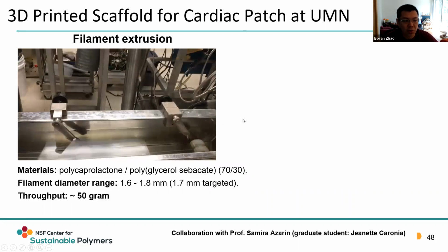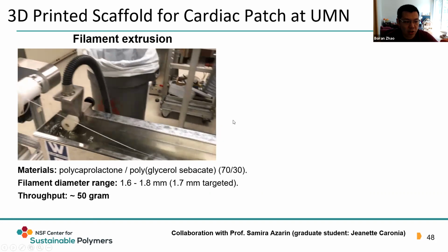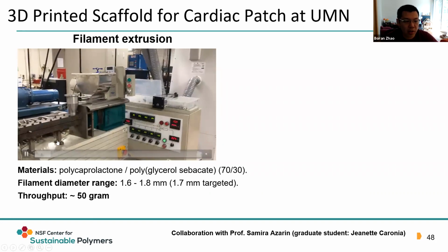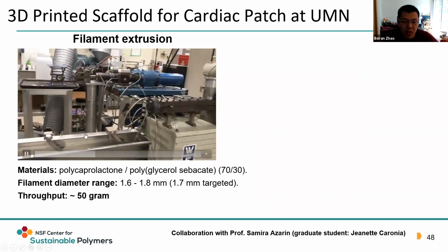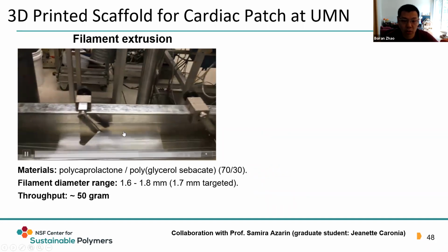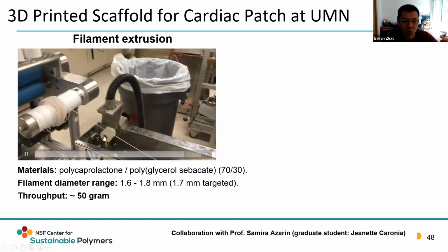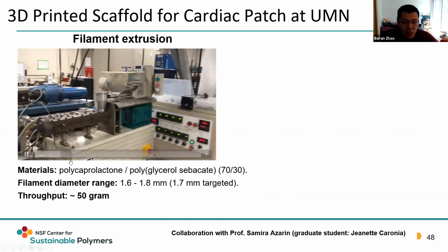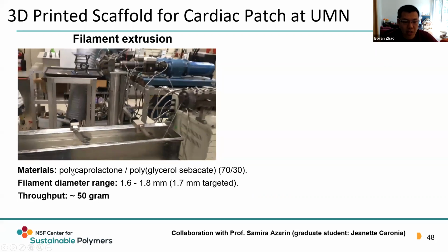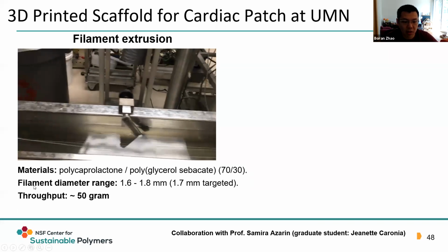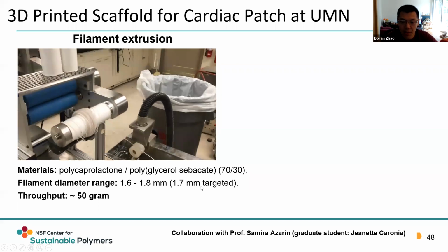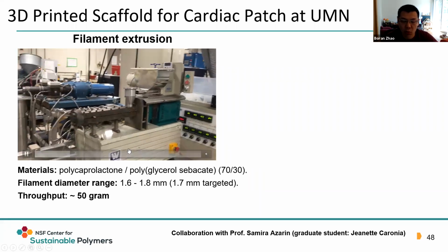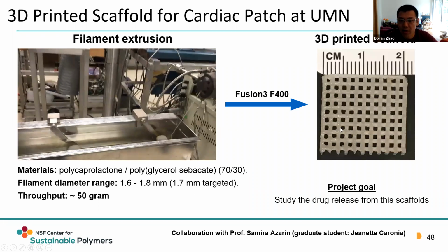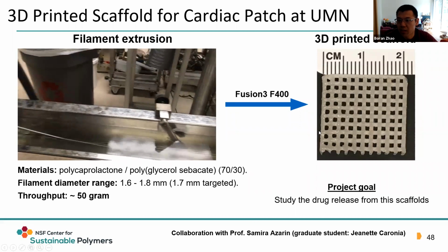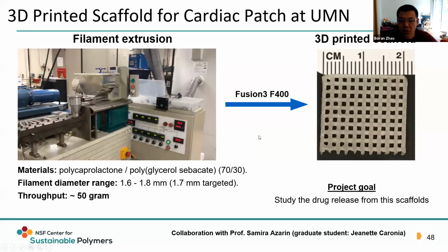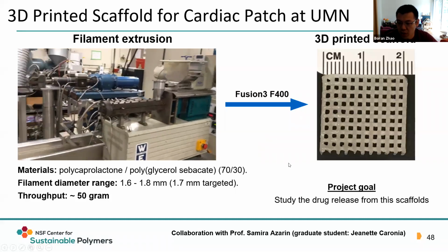The goal here is to 3D print a scaffold as a cardiac patch using FDM. And as shown in the video here, we use the twin screw extruder to make the filament. This is exactly the same extruder that my colleague Charlie has talked about before. As you can see, this material is a binary polymer blend, and we target the filament diameter to be around 1.7 millimeter, which complies with the requirements from the 3D printer. And here, as the picture on the right shows, this is the final product. And one thing we want to further develop is to study the drug release from this scaffold.